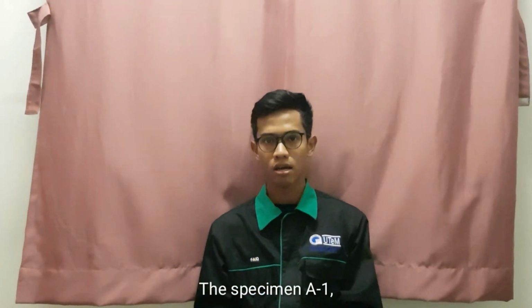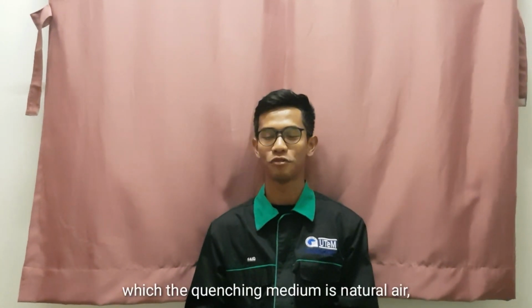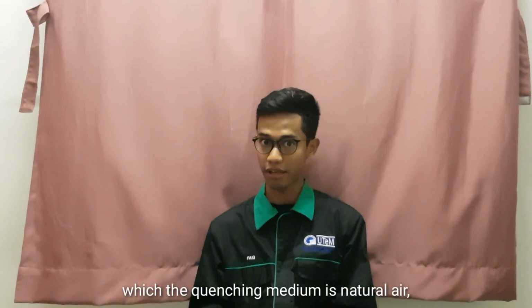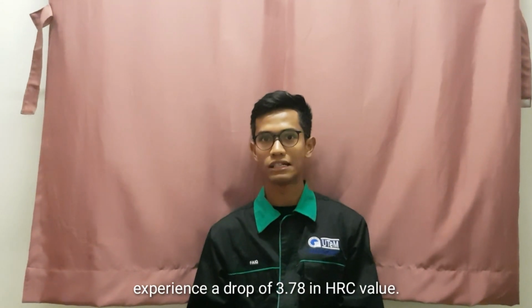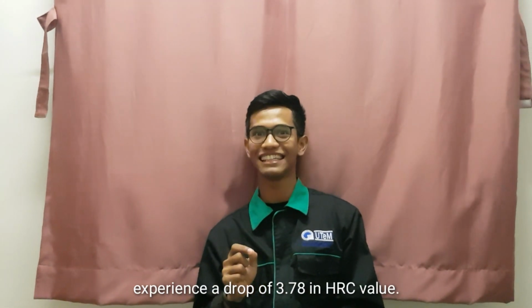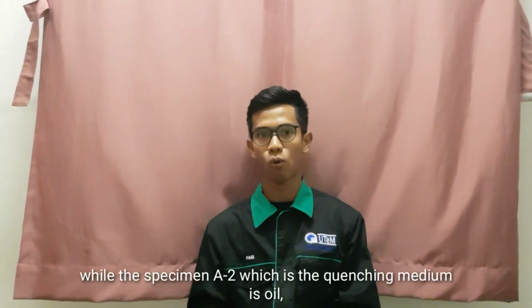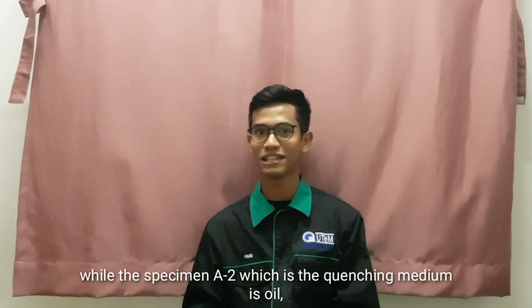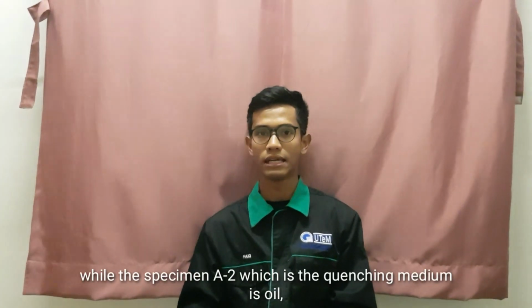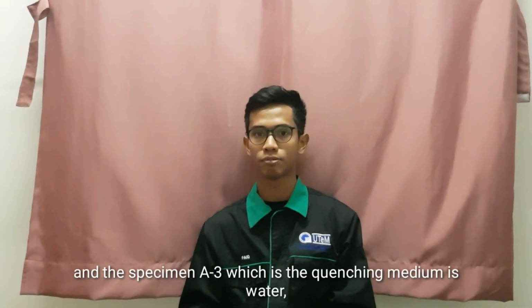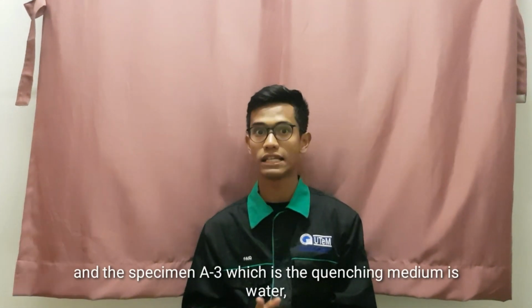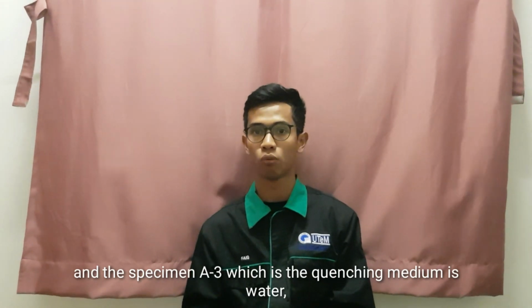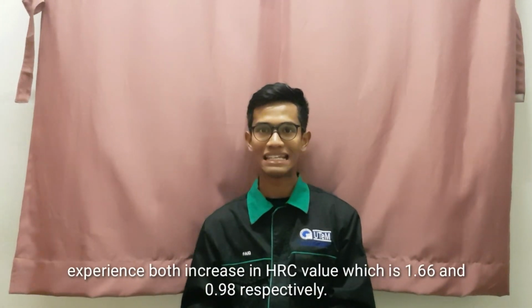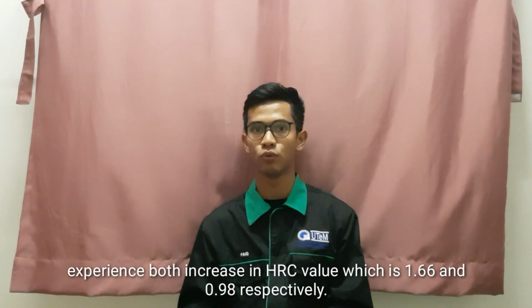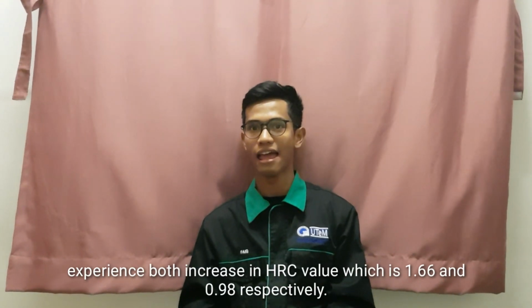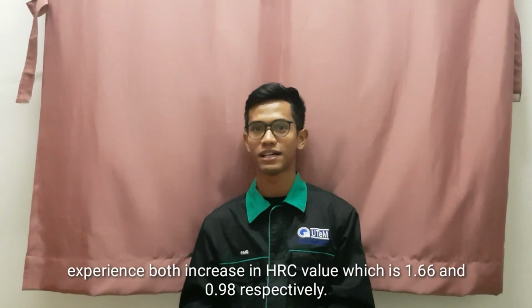in the cooling process. The specimen A1, which the quenching medium is natural air, experienced a drop of 3.78 in HRC value, while the specimen A2, which the quenching medium is oil, and the specimen A3, which the quenching medium is water, experienced an increase in the HRC value, which is 1.66 and 0.98 respectively.